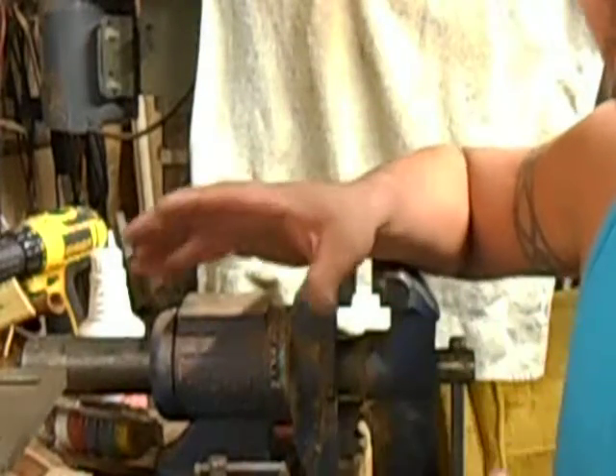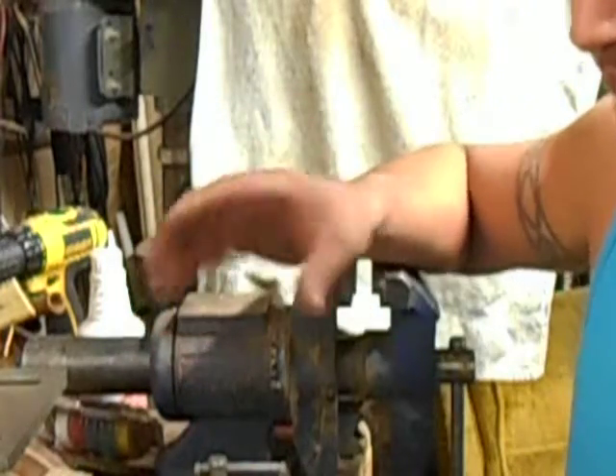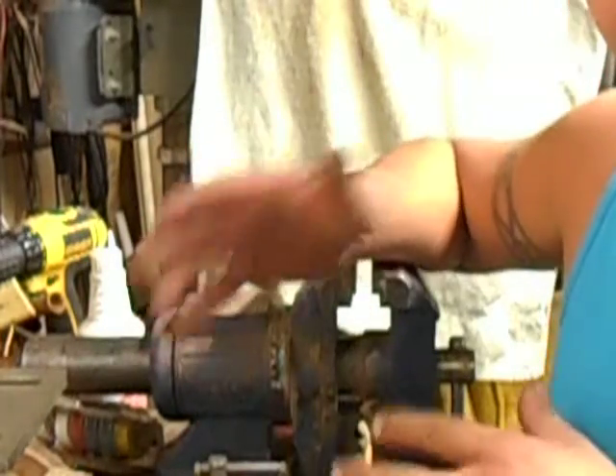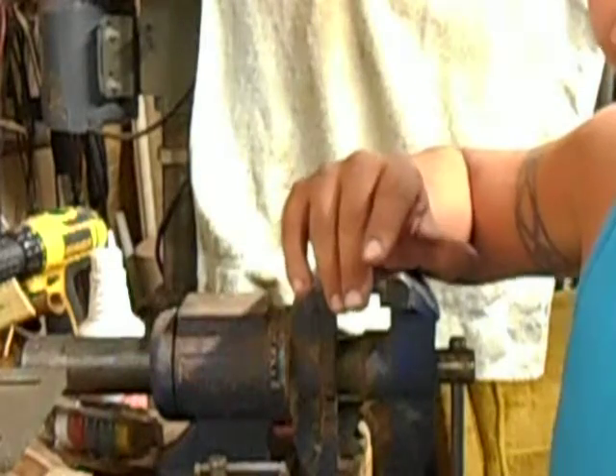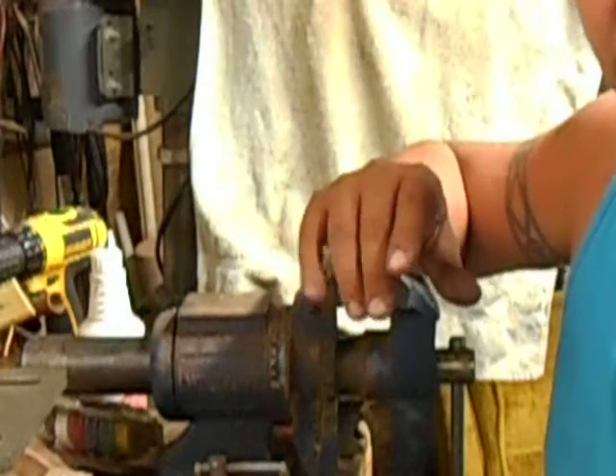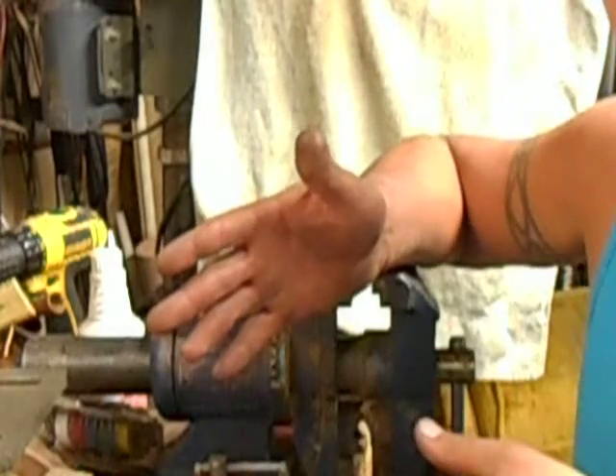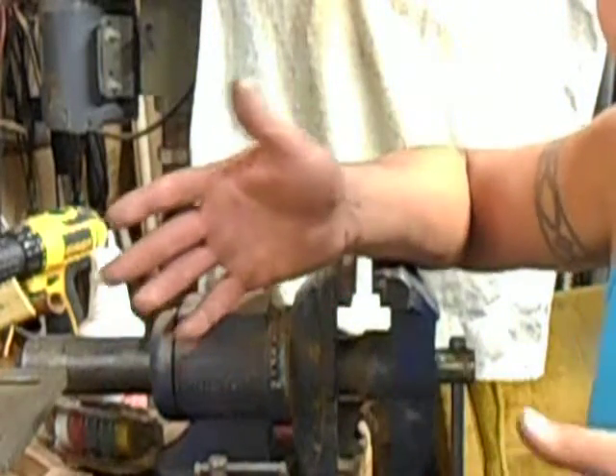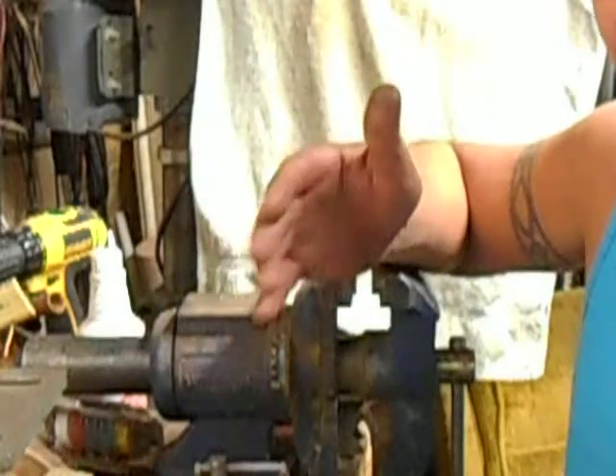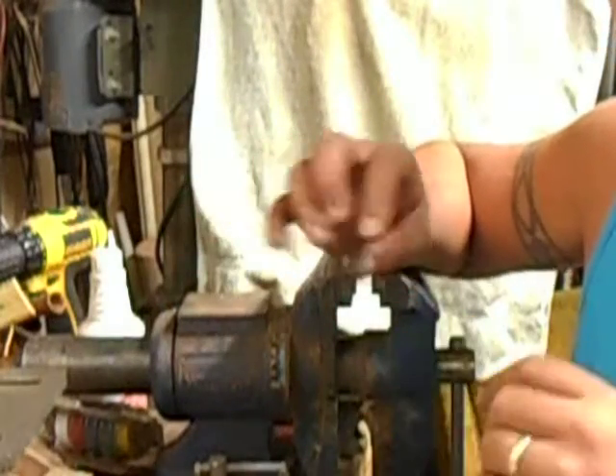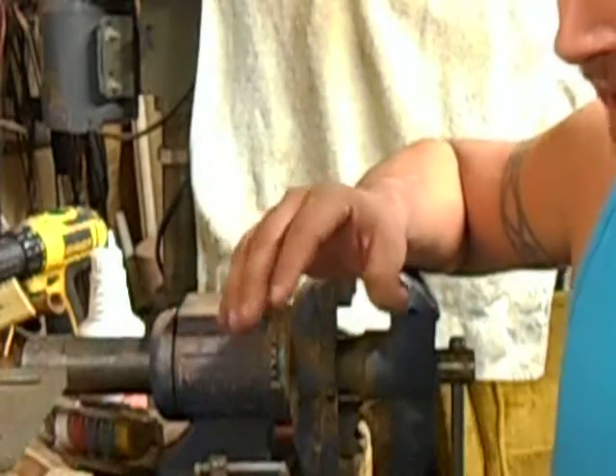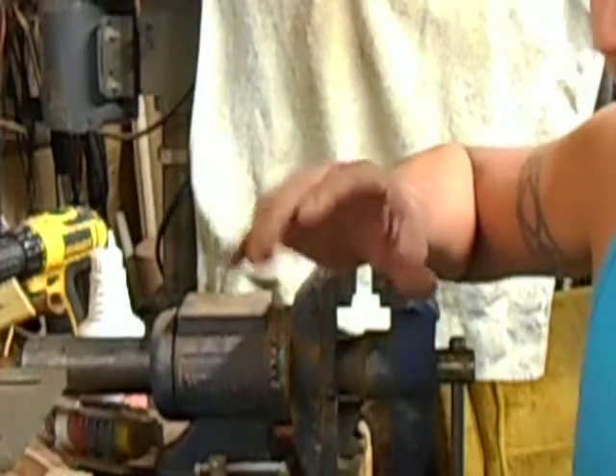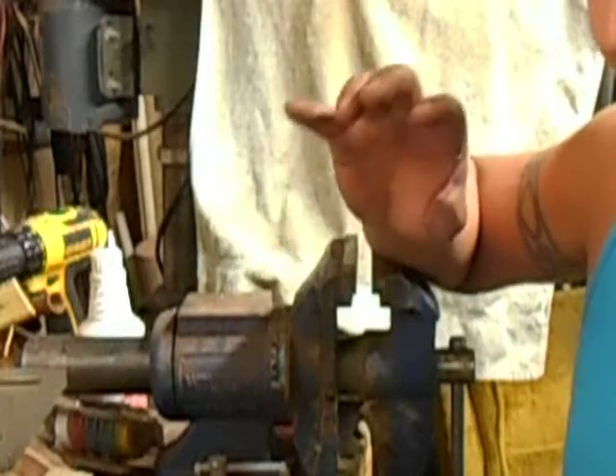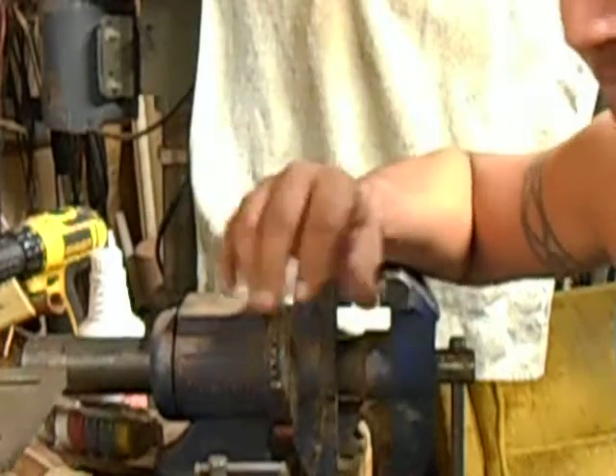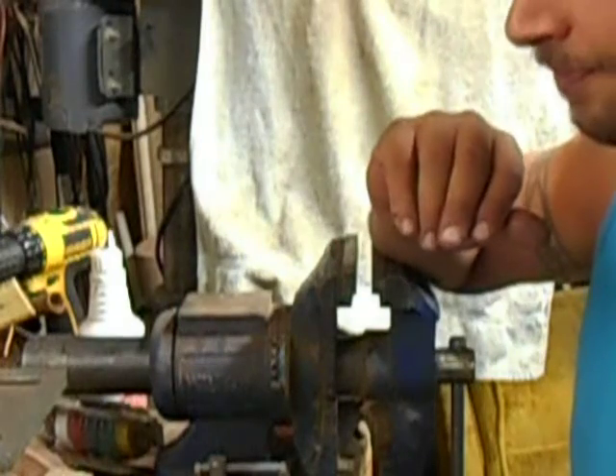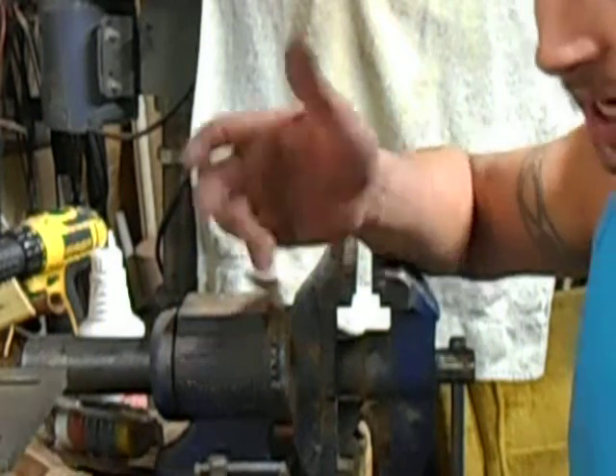Or the time at the hardening temp, so 1900 degrees for 15 minutes so far is the best. 11 minutes was a little bit too less. So what happens if I go 14 minutes at that temperature? Also, what happens if I drop my temperature 25 degrees? A whole bunch of little fine tuning here and there is still needed, but the base heat treat is so far really good and surprising me quite a bit. So yeah, I'm pretty happy with it.